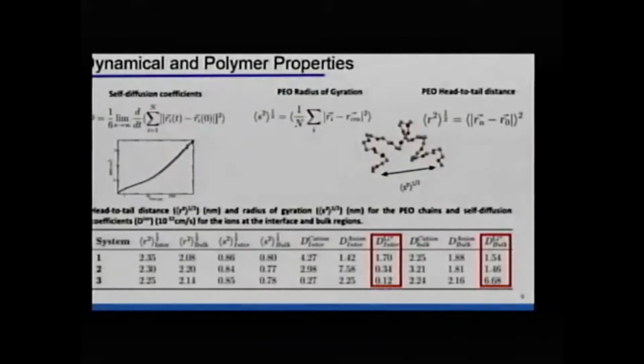But when we look at the self-diffusion coefficients for lithium in the interface region and in the bulk region, we see interesting behavior. If we look at system 1, we have the highest diffusion coefficient, more than 4 times higher than in the other systems. But when we look in the bulk, this is different. So we have a different behavior in the interface and in the bulk region.